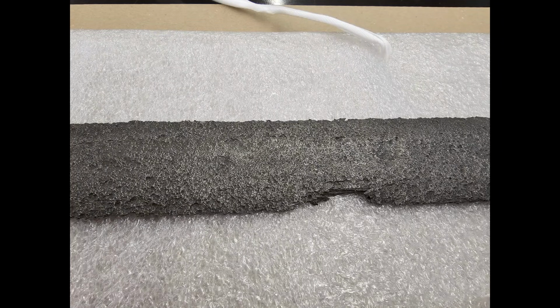It must be noted that both the edge steel and the cover panels show a very similar chemical composition, or chemical makeup, and are therefore assumed to be both of the half refined type of steel, with the big difference that the edge steel was refined by a fold and weld process, while for the cover plates it seems that the ingots were just hammered out flat and hot cut to match the sword blank.